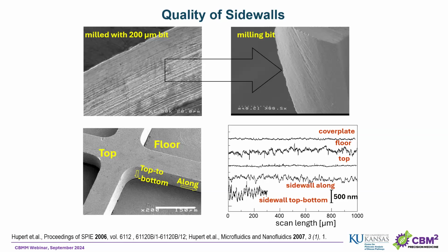The other factor to consider is that milling bits are mechanical tools, so there is some sharpness, some roughness on the cutting edge related to them, and this roughness will transfer into the machined part, right? And we can see this is a wall in brass, a side wall of the raised structure in brass cut with the micro milling bit, and you see the lengthwise wall. You can see the transfer of the roughness of the bit itself.